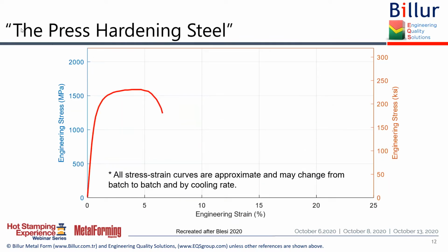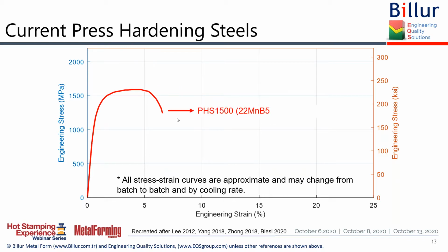Here we see the press hardening steel, because since 1984 to about 2011 there was only one grade, which is called 22 MnB5, and throughout the last decade we have seen several improvements in either having higher strength or having higher elongation or higher energy absorbing capacity. Let's put it that way. So once again, since the start of the hot stamping industry, we only had 22 MnB5.